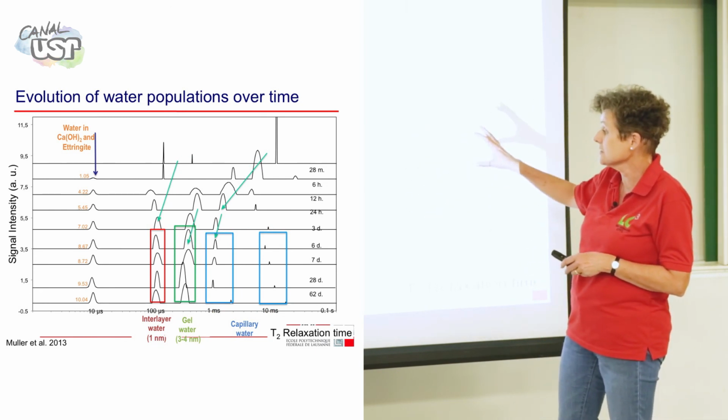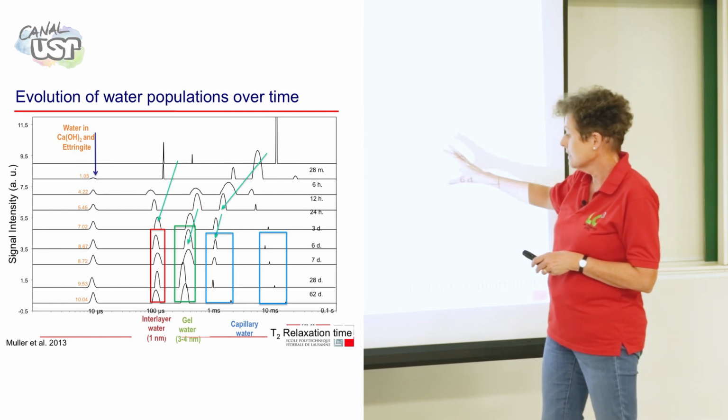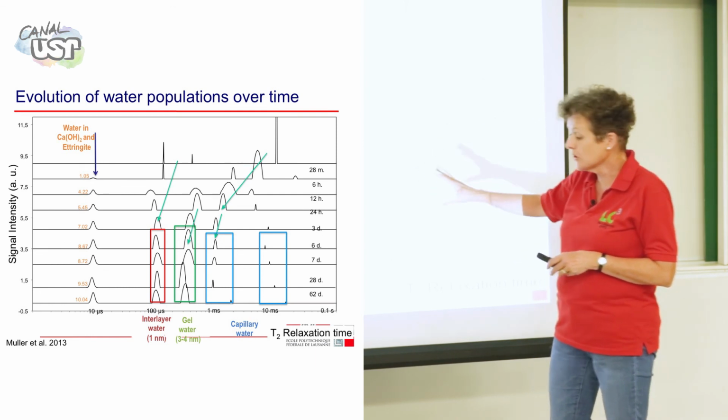Now, these are sealed samples, so that's quite explainable. But even though you've got quite large capillaries in sealed samples, as soon as you have setting, because of this chemical shrinkage we've talked about, the larger pores become voids. They become empty of water because the total volume goes down, and the overall volume of the sample is staying fixed, and therefore we have to create voids.